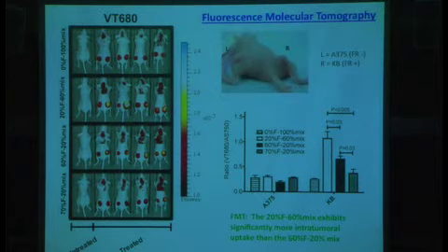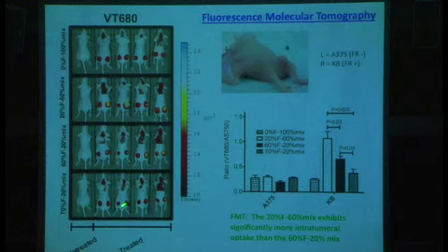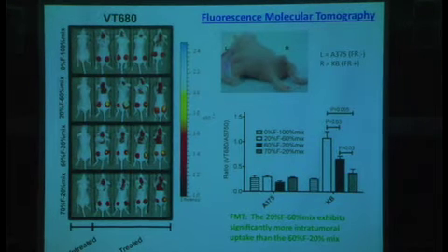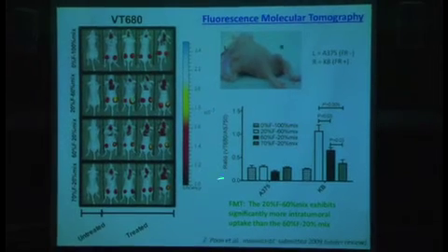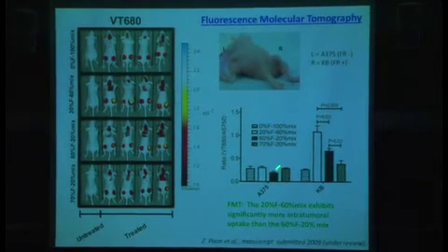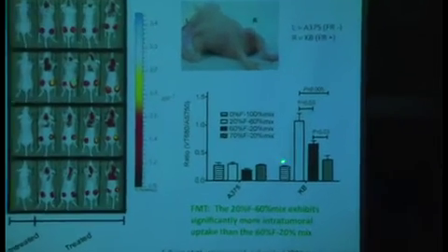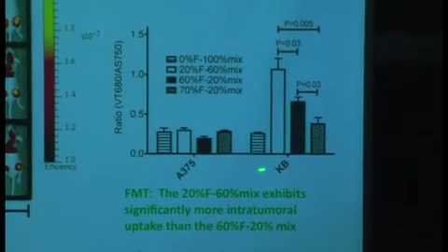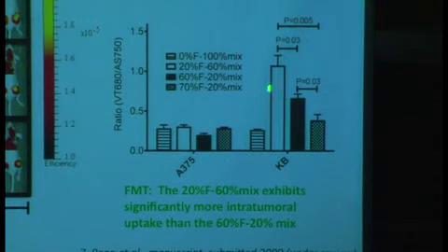If we actually make these clusters a little larger, here we're going to the 60% range, we see that we've gotten a decrease in the amount of uptake. And finally, we get to cluster sizes that are too large to allow sufficient binding for uptake. We also have done a great deal of quantitative analysis, in which we can get direct comparisons. And again, we see the same effect, that the 20% system is the one that gives us the highest uptake.